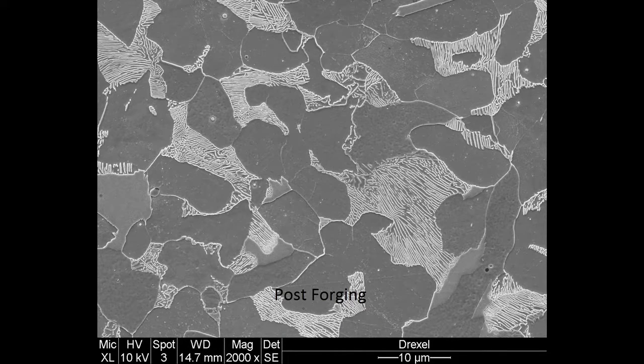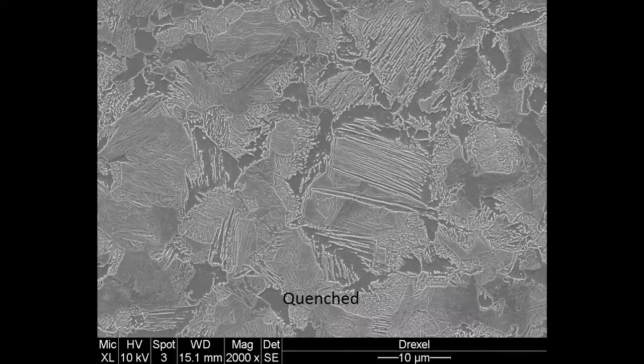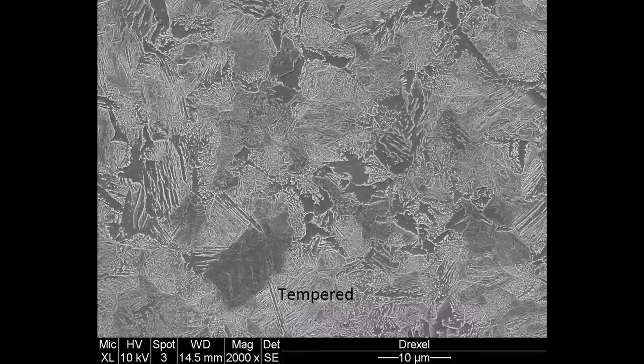The hot work performed in the forging process caused work hardening and refinement of the grain size. When the blade was heated above the austenite temperature and then quenched, it formed the metastable phase martensite, which is very hard and brittle. Tempering removes some of the martensite by heating the blade to a temperature high enough to allow diffusion, which enables the martensite to decompose into a more stable phase. This prevents the blade from being too brittle.